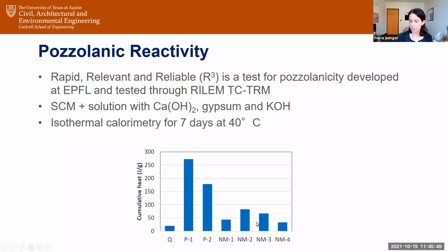They're not as low as the quartz, but they're pretty low. And so you start to say, well, what is it with these materials? They're fine grained. They have silica and alumina. What's the other part that we need? The other part that we need is we need them to be soluble. We need them to be glassy.